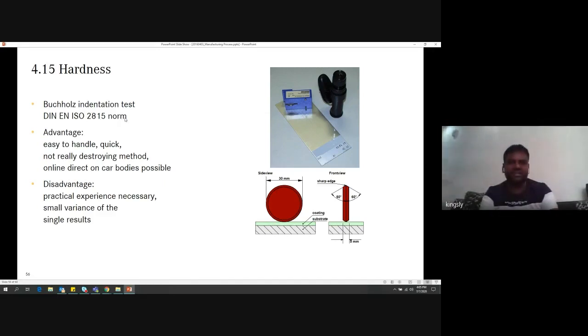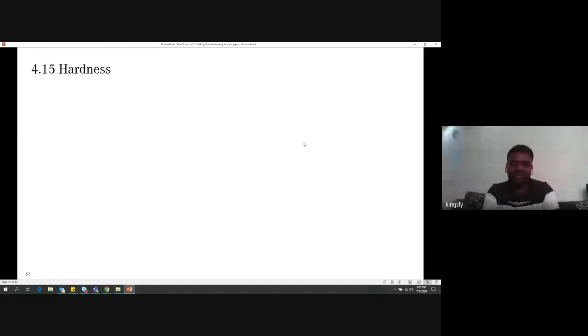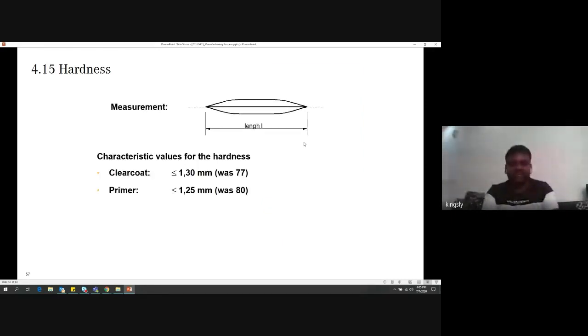For this test we also have an ISO standard norm. Based on this test, we will know that this paint won't crack maybe for 3 years, 4 years. So it will have flexibility and good adhesion with the steel parts. Basically this is done with the clear coat. The hardness test is done with 1.30 millimeter, and for primer we do it with 1.25 millimeter.